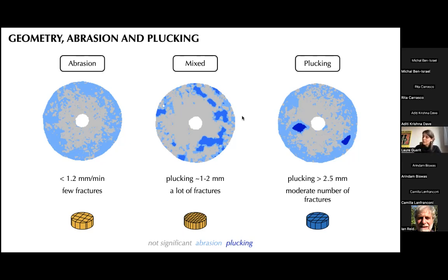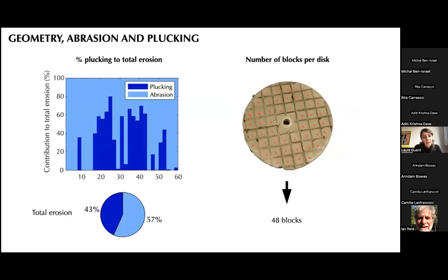So to go further, to try to formalize this observation, I need to define 2 additional parameters. The first one is the contribution of plucking to total erosion. So based on the map of plucking, abrasion, not significant that I showed you before, we simply calculate how much erosion is made by abrasion and how much by plucking at each time step. This is for the whole experiment, and then we simply take the average of it.